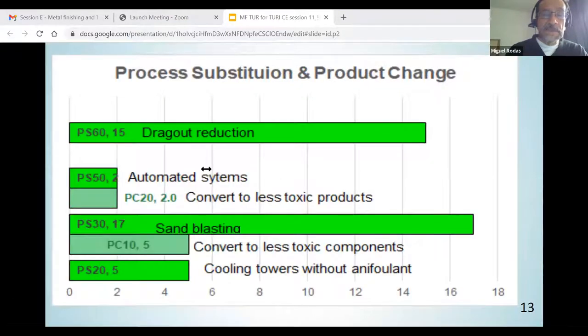And the next data that I collected is the process substitution and product change. I would say not most, but only 15 facilities are doing drag out reduction. And like I said, this is a very simple pollution prevention technique. However, not every metal finisher out there is taking advantage of preventing that type of loss by implementing drag out reduction, and then sandblasting, which is a physical means of surface preparation. On PC, or product change, the 2 over here belong to 2 facilities that are moving away from the lead plating and moving into tin only plating.